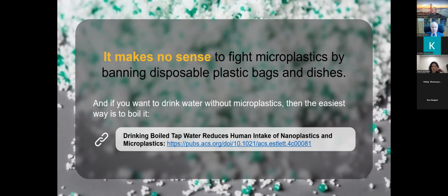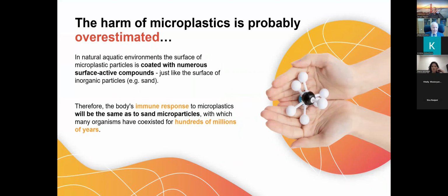So the general conclusion is that the main direction of the fight against microplastics is not always correct. And the most important thing is that the harm of microplastics is probably overestimated, because plastic is never in distilled water. It is in a natural aquatic environment, and therefore the surface of any microplastic particle should be coated with numerous surface active compounds, like remnants of some biota in the water. And this will be just like the surface of inorganic particles, like sand. So the core is not important.